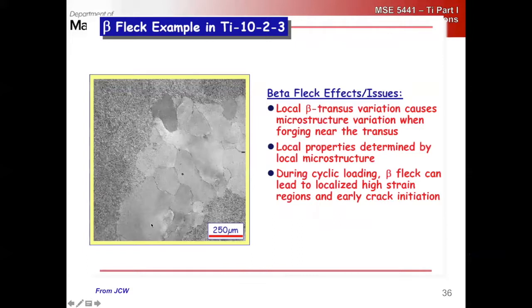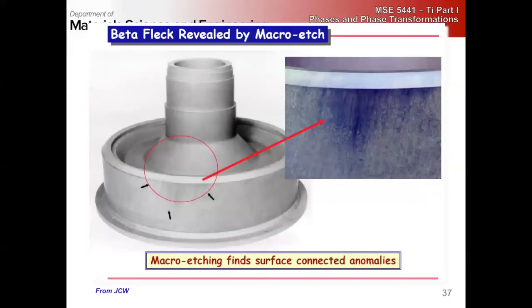But here's the issue with beta fleck, right? You can see the great disparity in grain size, right? Grains that are a couple tens of microns to half a millimeter, right? So we get a variation in the beta transus, right? And then the local microstructure evolution and properties are going to be very different. And then if we have cyclic loading, we've got localized high strain localization in these larger grains, and it's going to lead to early cracks. All right. And this is just some macro etching that was done to highlight the issue of beta fleck.